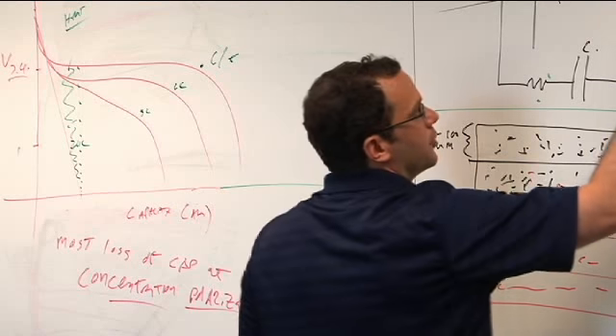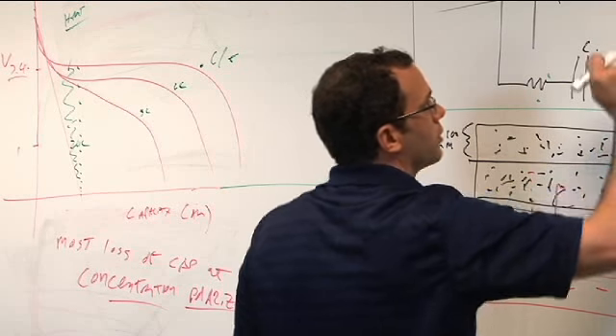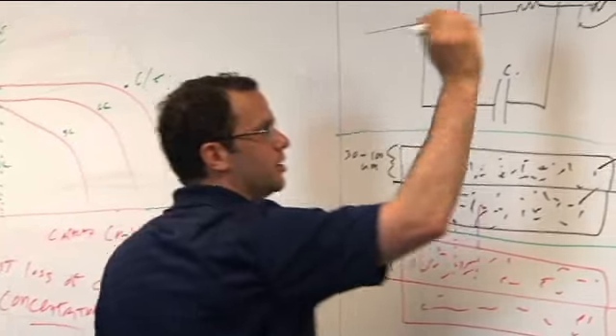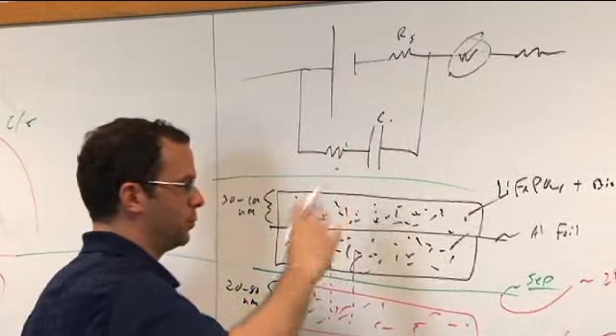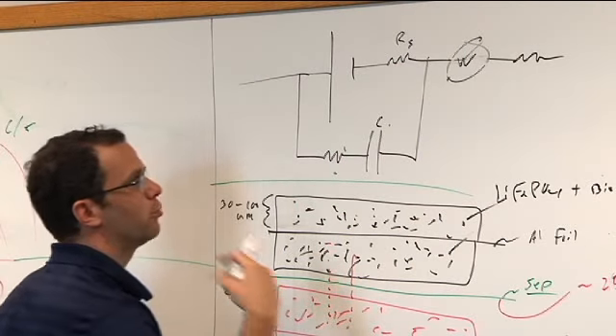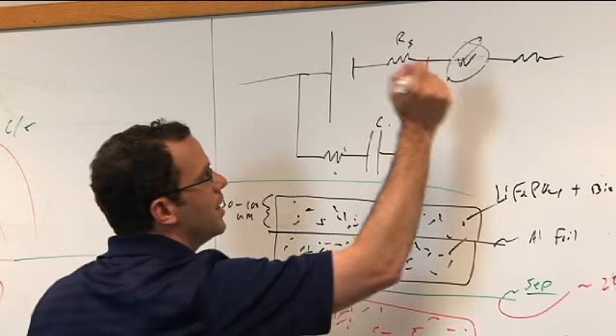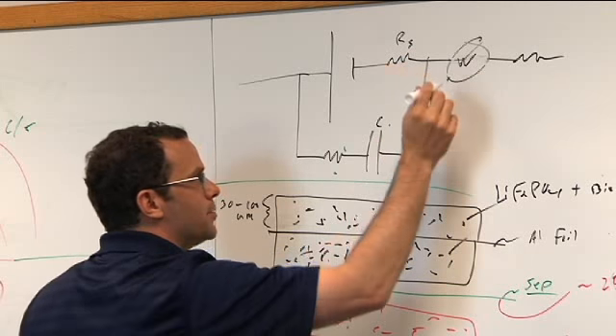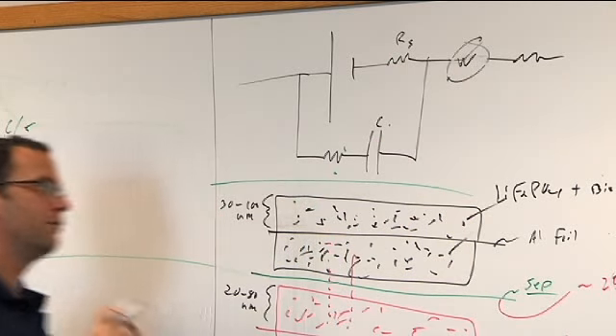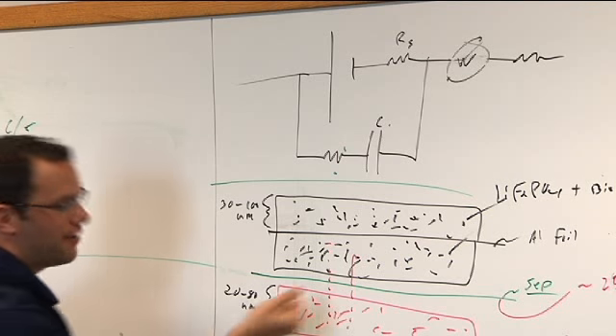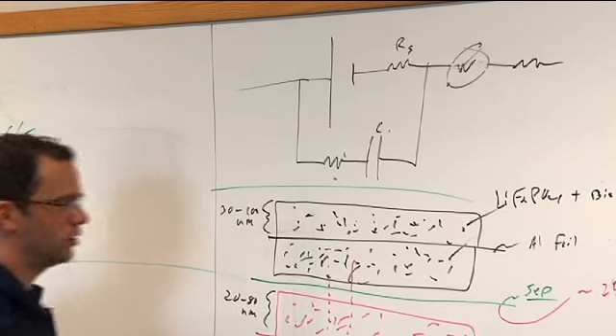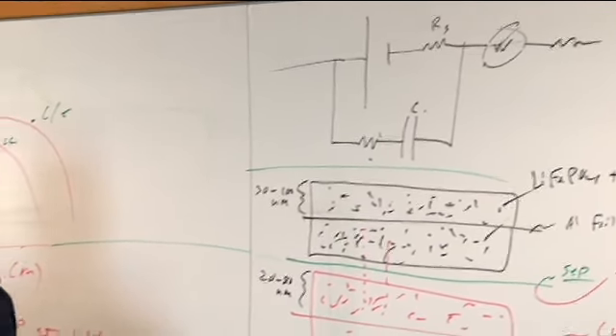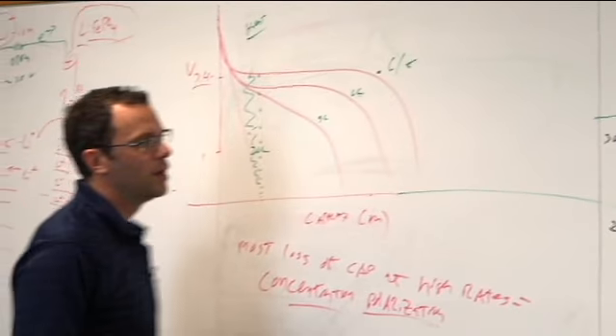And that is captured in the equivalent circuit model by this Warburg coefficient, which is diffusion-based, and there's probably multiple ones. There's one for the anode, one for the cathode, one for the separator, but we can just lump it into one. The key with the Warburg is that it captures the ability of the lithium ions to actually navigate through my electrode structure and indeed navigate through the inside of my crystal materials as well.